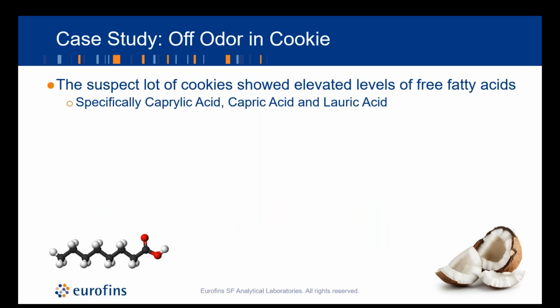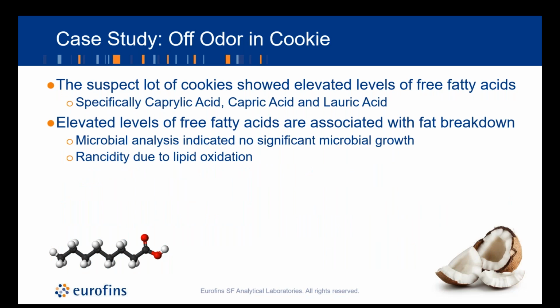These compounds are free fatty acids, and elevated levels of free fatty acids are associated with fat breakdown. They also have sweaty, cheesy odors associated with rancidity. Microbial growth can cause the production of these free fatty acids, but in this case, we did also do a microbial analysis of the cookie samples, and there was no indication that there was excessive microbial growth compared to the control, so we could rule that out as a cause. So in this case, we were looking at the production of these free fatty acids and rancidity due to lipid oxidation.